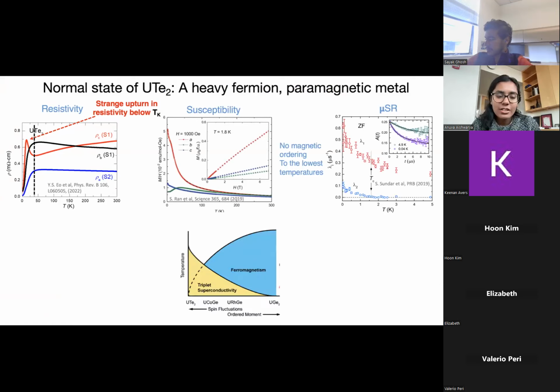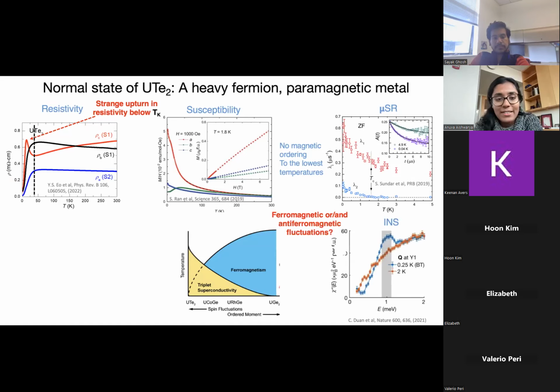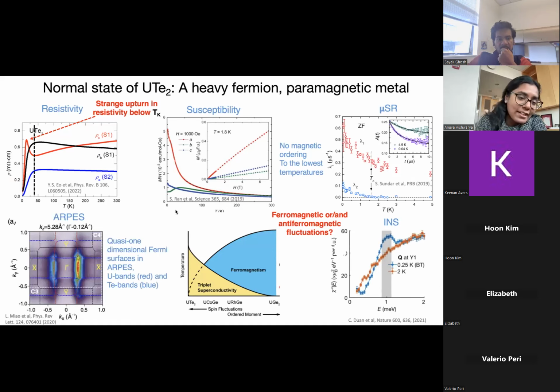So it's believed that UTe2 is the paramagnetic end of the ferromagnetic series of uranium compounds, where we have ferromagnetic fluctuations and superconductivity coexisting, which has given rise to the theory that it probably harbors triplet superconductivity. But all's not well, because some recent inelastic neutron scattering measurements found antiferromagnetic fluctuations, which are correlated with superconductivity. So it's still not clear which one of these plays a major role. ARPES measurements found quasi one-dimensional bands originating from uranium and tellurium.